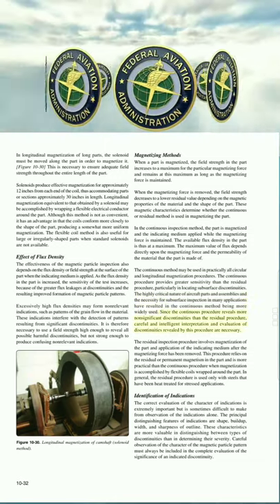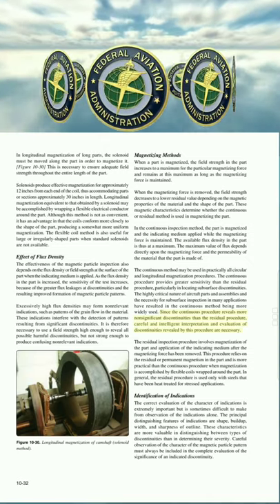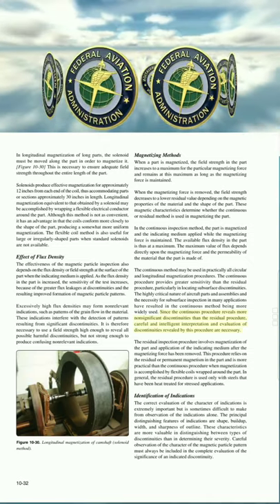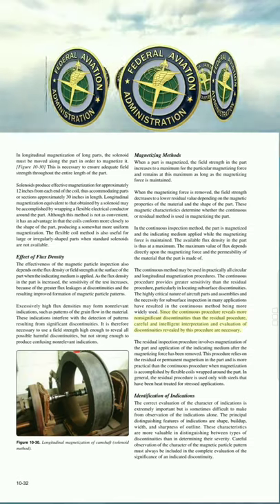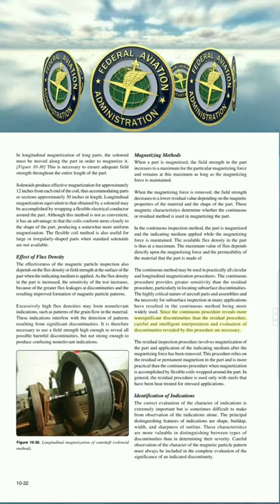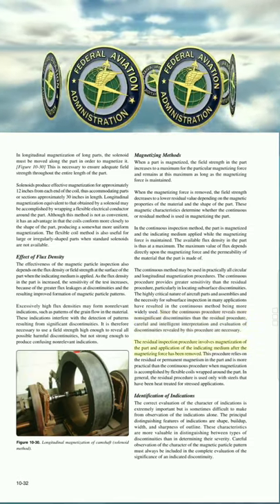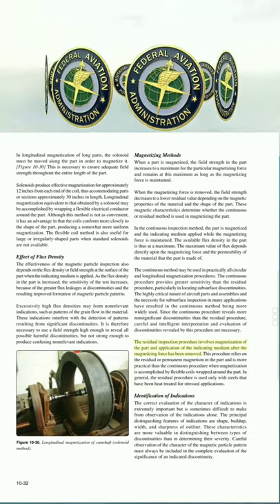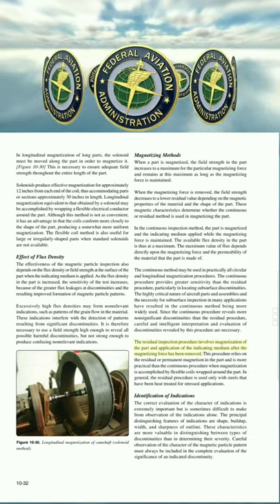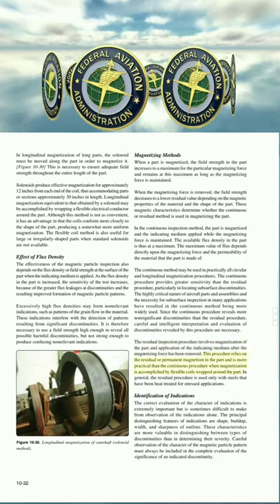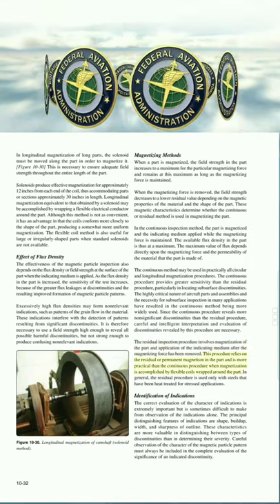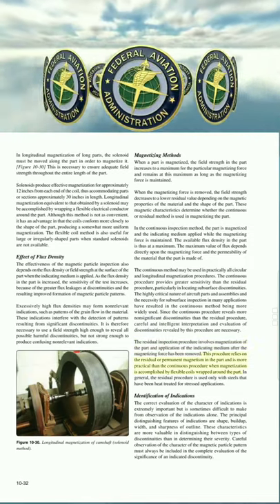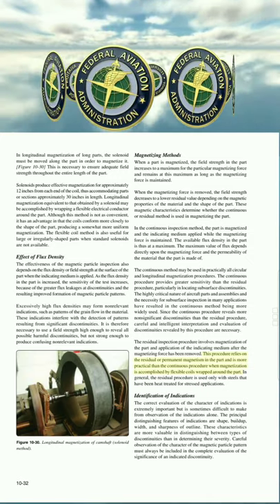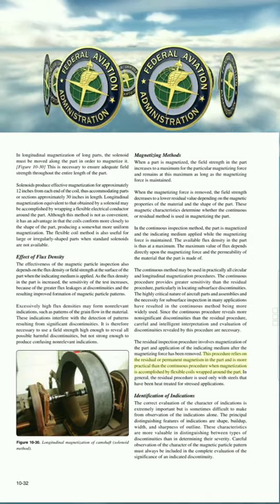Since the continuous procedure reveals more non-significant discontinuities than the residual procedure, careful and intelligent interpretation and evaluation of discontinuities revealed by this procedure are necessary. The residual inspection procedure involves magnetization of the part and application of the indicating medium after the magnetizing force has been removed. This procedure relies on the residual or permanent magnetism in the part, and is more practical than the continuous procedure, when magnetization is accomplished by flexible coils wrapped around the part.